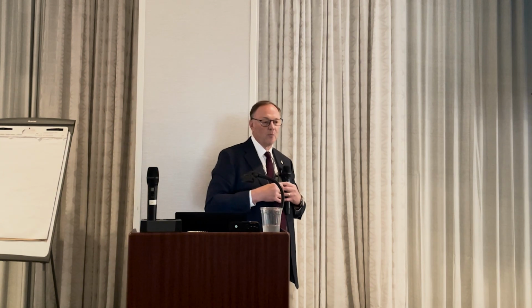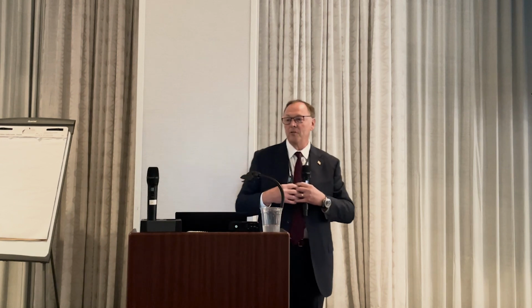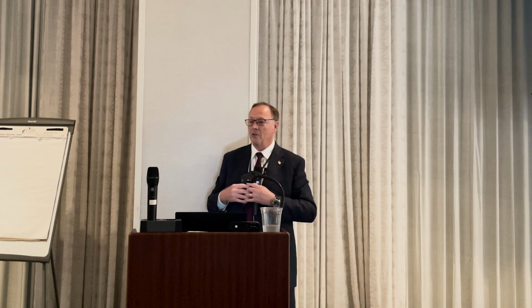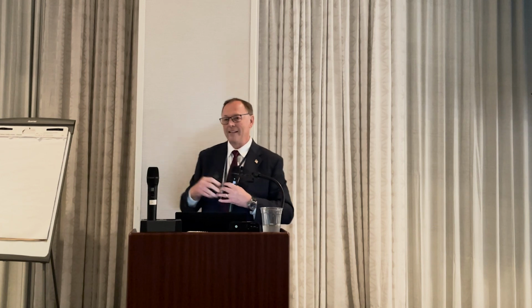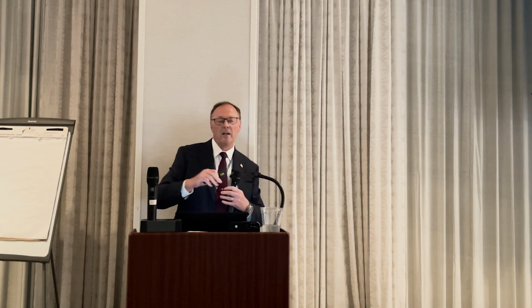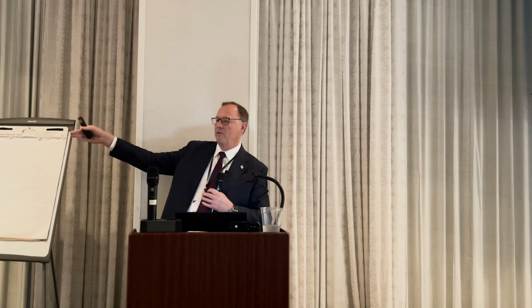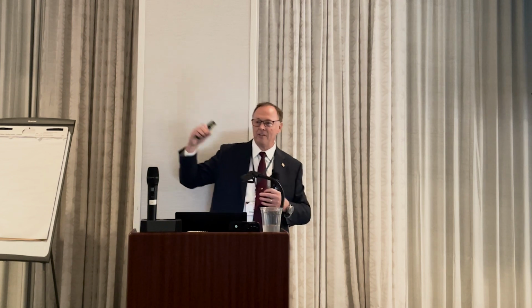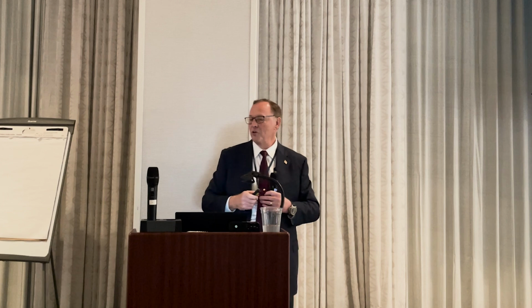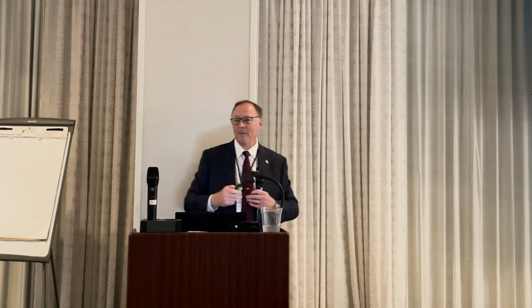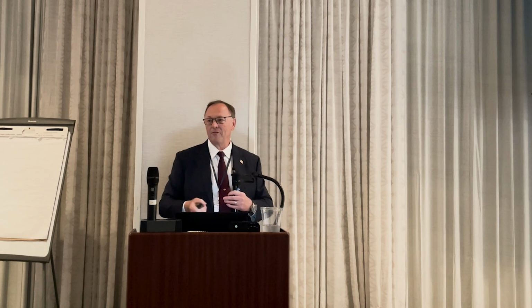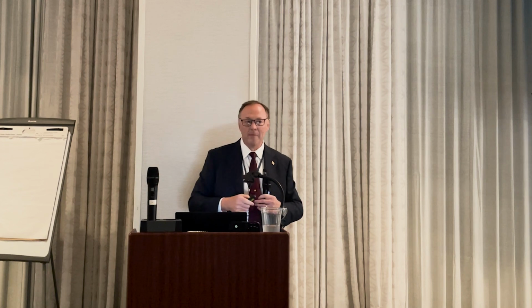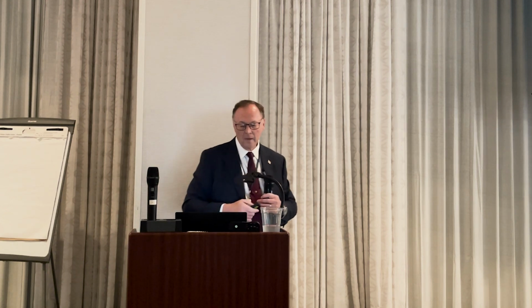So where we have those critical surfaces and those things are important to us, we know that, okay, we want these post-cured. You don't have to post-cure everything, but where we need that little extra and where we want to get to 20 years of life versus 16 or 17 years of life, because a few years is usually, in most cases, a few million dollars. That doesn't sound like a lot, but if you have to rip it out that much earlier, it makes a big difference.